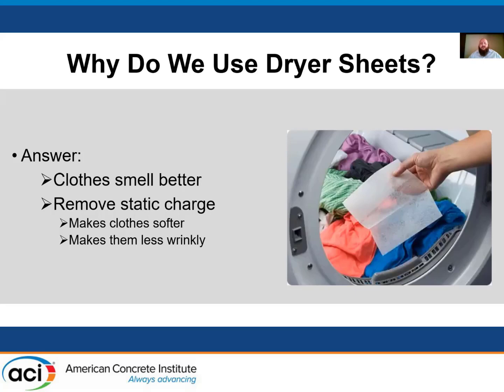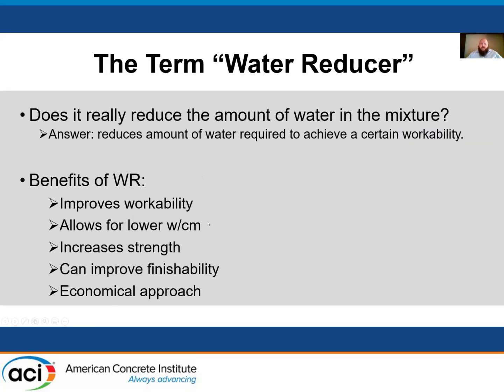So in essence, it changes the surface energy of your cement particles so that they can flow outward more. They can spread out, you don't trap a bunch of water in there, and the water can be spread out better too. And so the term water reducer doesn't actually reduce the amount of water in the mix, but it does reduce the amount of water required to achieve a certain workability. So just realize that's where that term came from.